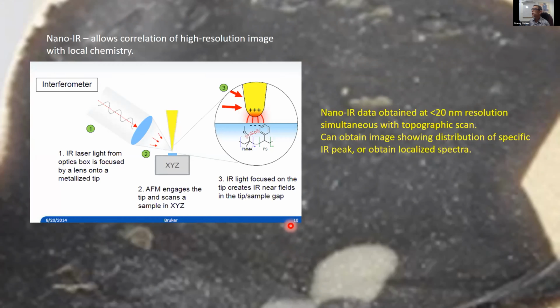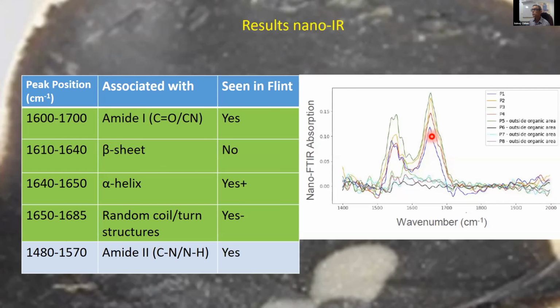One was a nano-IR. Nano-IR uses some of these principles, which we heard already in this session. You can create kind of an enhanced field at a sharp metal probe close to a surface, so you can be in the near field and look at IR spectra with resolution which is way, way below the diffraction limit. And this can be done either in the form of taking a spectrum of a certain point in the surface, or by locking in on a particular wavelength and mapping out the spatial distribution of that chemical species which is represented. So we see a result of that here.